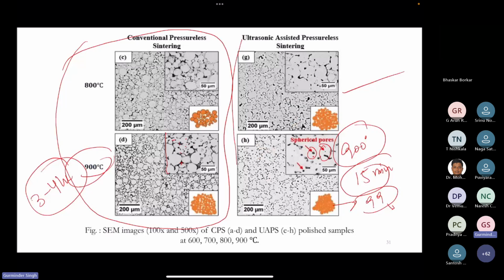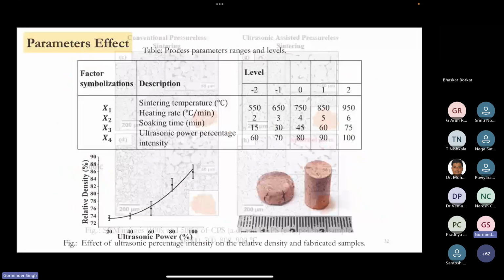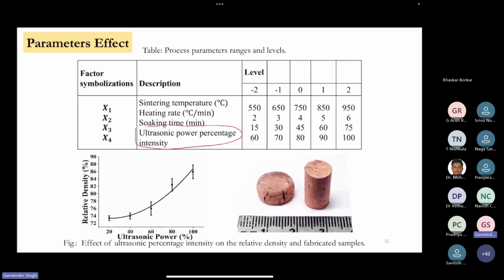So this is the example we have seen with the microscopic images, and we are getting spherical pores at lower temperature as compared to the conventional sintering process. Other than this ultrasonic vibration, there are a few other sintering parameters also affecting this process. So we have tried to do some design of experiment using RSM methodology to make these copper cylindrical samples, do compression testing and measure the density.